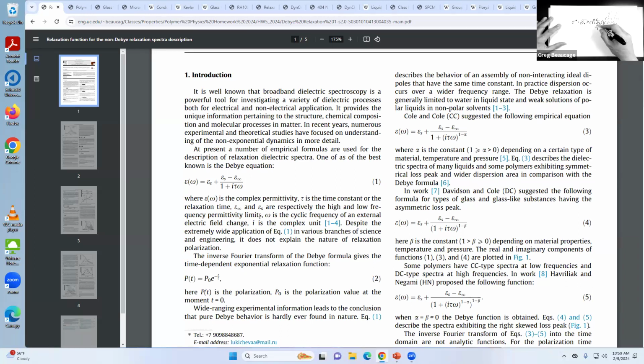If you look at G double prime in terms of frequency, the numerator increases linearly, tau omega, and the slope of that is tau. The bottom part decreases because as omega gets larger, it will override the 1. So that decreases like that, and when you multiply those two together you get this. At high frequency, it's a glass. At low frequency, it's a liquid. And then you have this magic number where tau equals omega, and that gives you the peak. When tau equals omega, this is 1 over 2, 1/2 i. So you have that magic number where they match up.